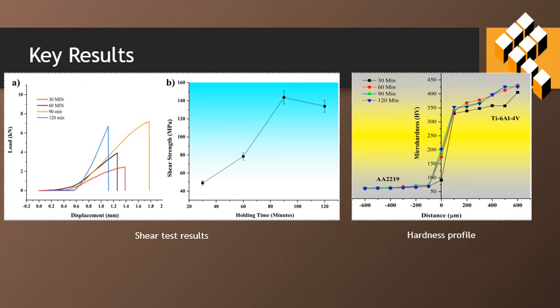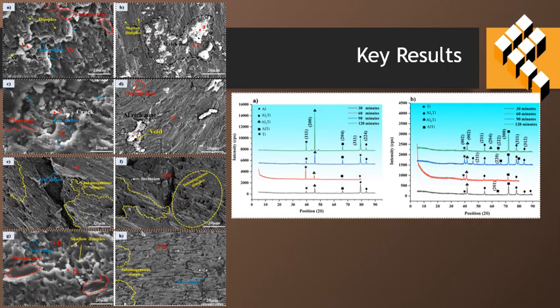Similarly, the microhardness is evaluated across the joint interface, and it is observed that the hardness at the joints is increased with increase in the holding time. The increase in the hardness is mainly attributed to the formation of hard intermetallics. Fractured surface and their fractography is shown in the figure. The XRD curves clearly indicate the formation of intermetallics such as Al3Ti, Al2Ti, AlTi in addition to the pure Al and Ti peaks.